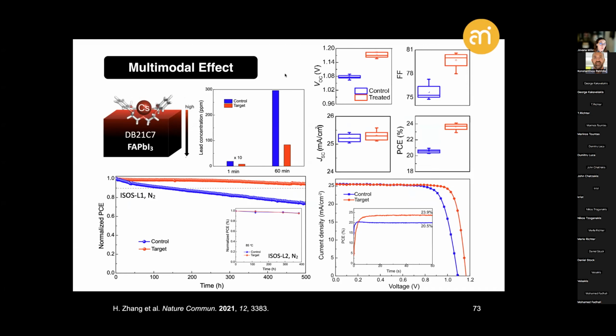of these materials, but more importantly, their operational stabilities, even at elevated temperatures, which highlights the importance of this multimodal host-guest complexation effect that relies on a synergy between the host binding competitively these ions at the interface that act as defects and possible ion migration sites, its hydrophobicity, but also the cesium cations as a guest stabilizing the resulting perovskite architecture and the resulting host-guest complex delivering the effect.